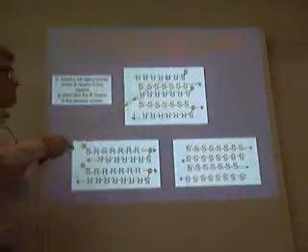And now the question was, what were these beta sheets that we expected in this particular crystal? And from the crystal structure, we anticipated that these are actually racemic beta sheets. That you have a layer of poly R, and you have a layer of poly S, you have a layer of poly R, and you have a layer of poly S. Now the question is how we can differentiate between these, because spectroscopically they are very similar to the pleated beta sheet that we found in nature.